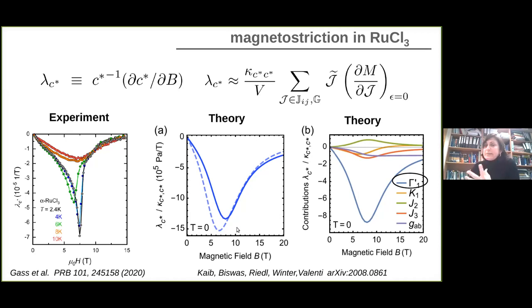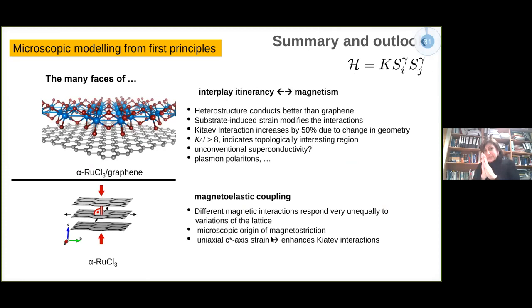And the nice thing about doing these simulations is that we can disentangle which contribution is the one that is most important for this effect. And what we see is, in fact, that gamma prime is the most important contribution for describing this effect here. And with that, I'm coming to the end of my talk, where in the first part, I hope I